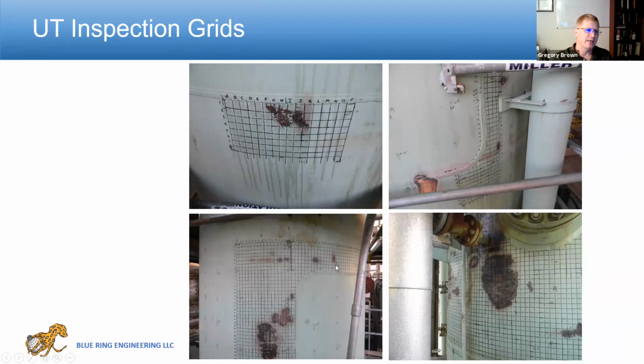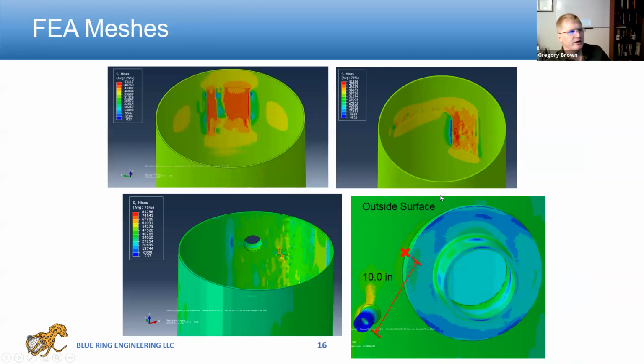A level 3 assessment was done on the other areas. You can see some pictures of this here. Again, anytime you see these colored lines, it means finite element analysis was done. There's nothing magical about this. It is just a very fancy calculator used to compute stresses and strains, etc. So what you're looking at in the upper pictures is the corrosion around that patch plate. In this case, we used the inspection grid and put it into a computer model, using all the inspection points. What you're looking at here is stresses under those operating conditions, pressure and wind, around that location. You can see some higher stresses occurring where there was this corrosion. So the corrosion is actually causing a region of high stresses.